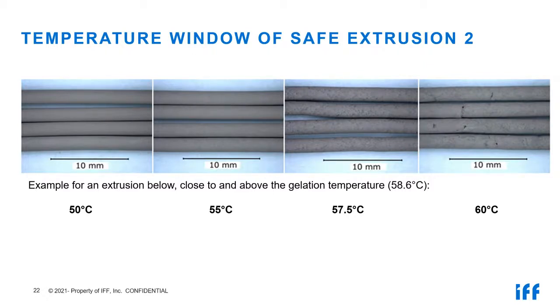Finally, the extrusion test at 60 degrees, more than 1 degree above the gelation temperature. This is a disaster. You never would sell this. Definitely this is all off spec, and the extrusion here in picture 4 is all defect. This is just for demonstration purposes to show how important it is to stay away from this gelation temperature. Next slide.